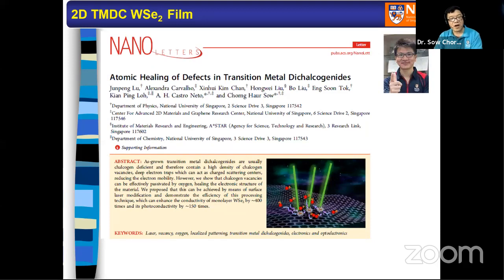Okay, this is the story of WSe2. There are different ways to get WSe2. Some use mechanical exfoliation, but in our lab, we use a CVD grown process. But in the CVD grown process, one of the typical characteristics of the transition metal dichalcogenide film is that there's a lot of vacancy. So now imagine that WSe2 is grown and we use a laser beam to try to modify it. The as-grown WSe2 has a lot of potholes because there are a lot of selenium vacancies.